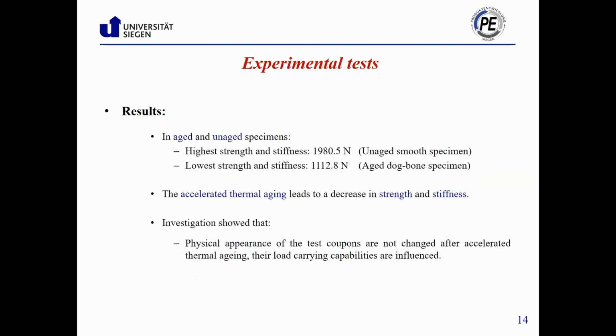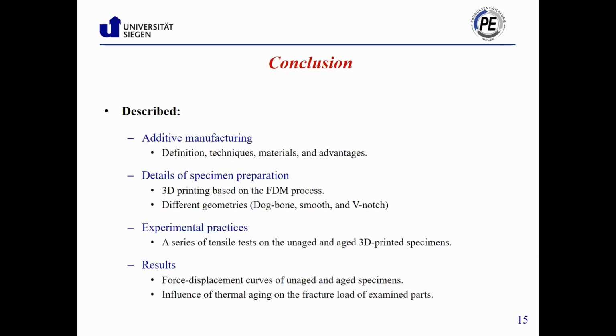Tests indicated that the unaged smooth specimens showed the highest failure load, and the lowest failure load belonged to the aged dog bone specimen. Moreover, experiments confirmed that the conducted accelerated thermal aging leads to a decrease in the strength and stiffness of the components. You can see the values from the experimental test. The conducted test also showed that there is a sudden failure in the specimens, and all groups of the specimens are not plastically deformed during the test.